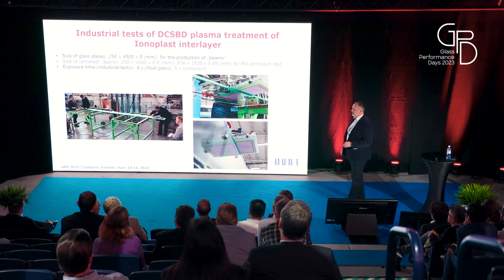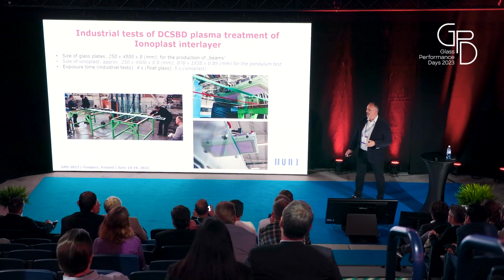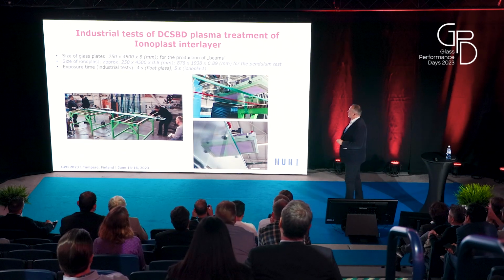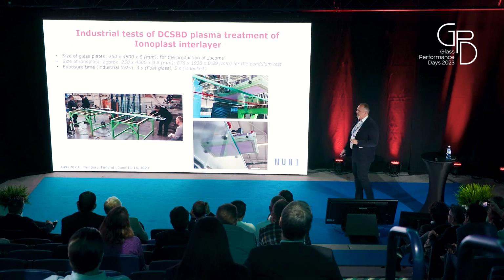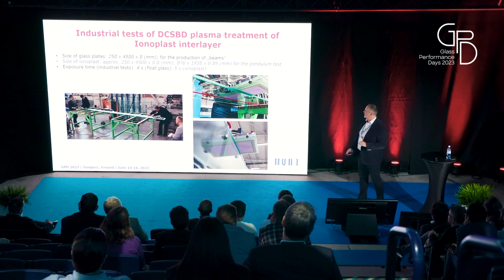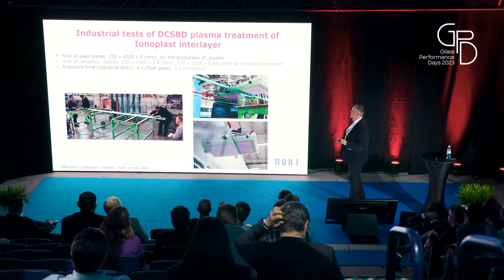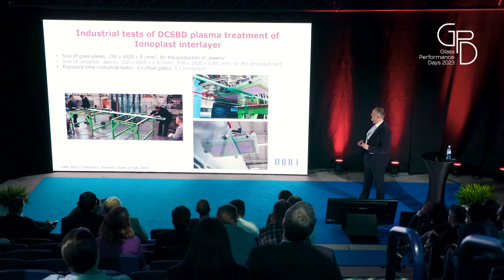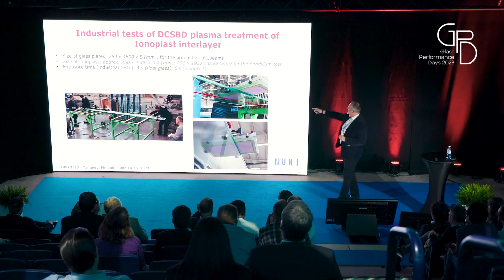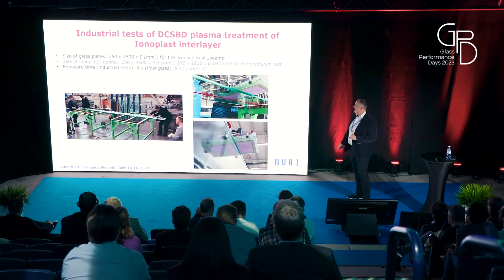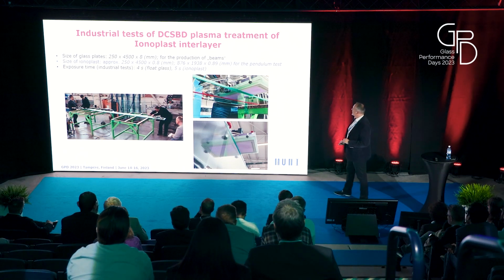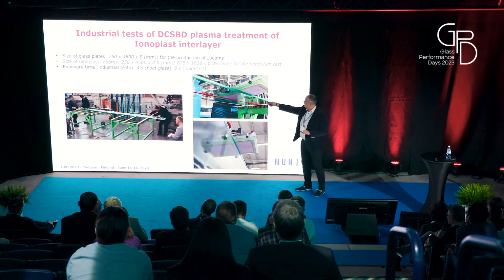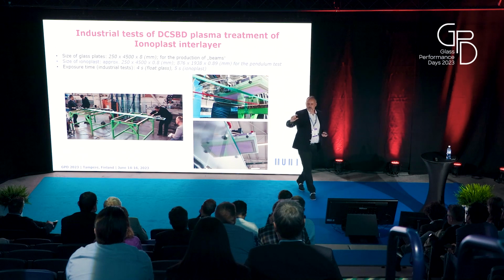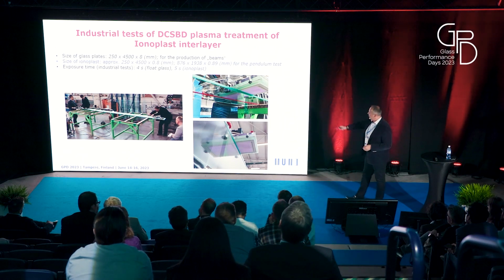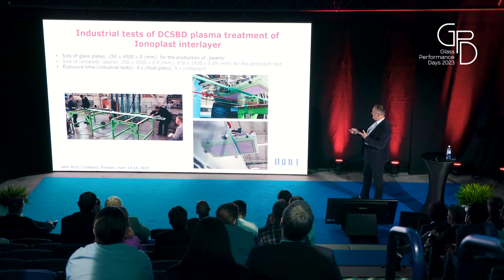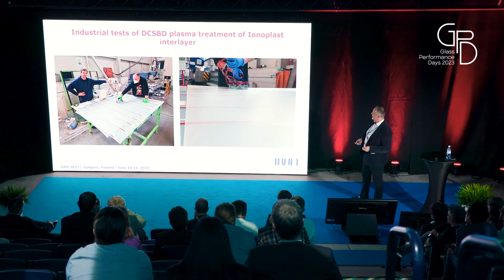So this was the overview of some experiments in the laboratory, but we also tried to do the treatment directly at the industrial partner premises. Here you can see the real photo when we were preparing the glass beams with a length of 4.5 meters. On this picture you can see the activation of glass with a thickness of 8 millimeters by a plasma unit. You can see ball bearings which are here, and using them we are able to keep the required distance of 0.3 millimeters. On the bottom picture you can see the treatment of Ionoplast.